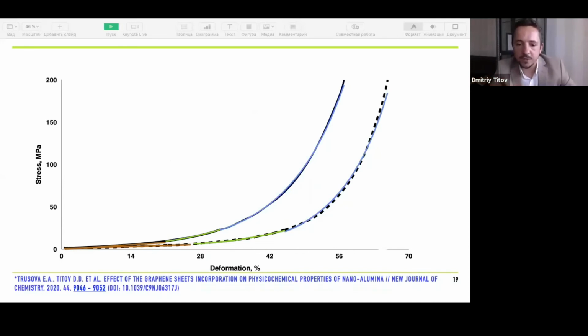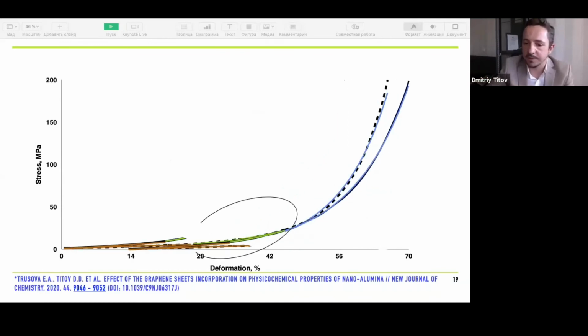What we see in the following 2 stages: for the pure alumina, the middle section is much longer than it is for the composite powder. The particles still have a lot of space to adapt and take a place that is more convenient from the energy point of view, and compact as much as possible. The deformation curve is 2 times larger for the pure alumina than for the composite, as graphene sheets inhibit adaptation.